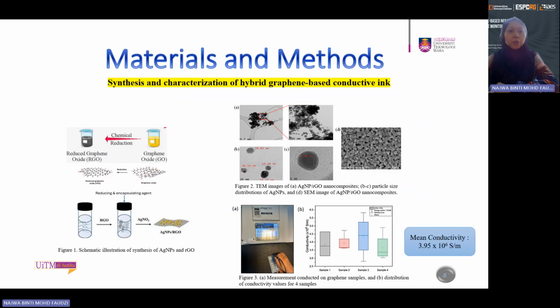So let's go to the materials and methods parts. We start with the synthesis of the hybrid graphene-based conductive materials. The synthesis has been conducted through chemical reduction method. The reduced graphene oxide is produced when further reductive exfoliation treatment is applied to the graphene oxide.